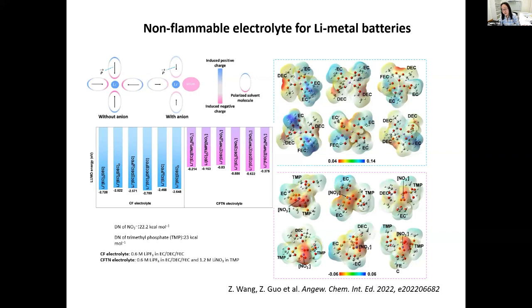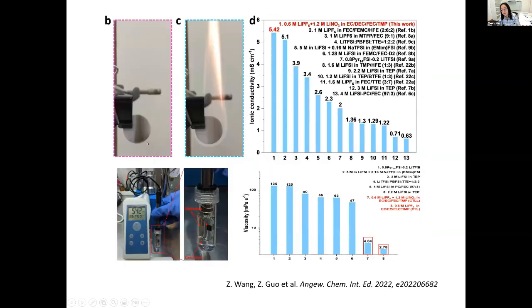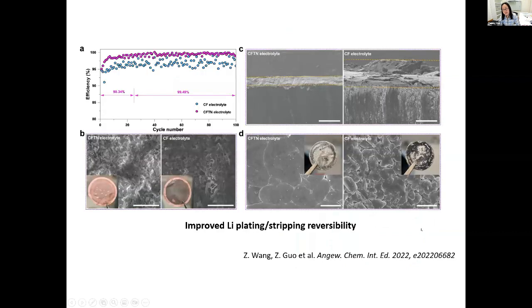Therefore, it can reduce the polarity of the electrolyte and make it more stable. And also from the calculation, we found that the LUMO value of the electrolyte increased, indicating the electrolyte is more stable. And from the MD calculation, we found that for all 6 possible solvation clusters, the ESP value decreased, suggesting that lithium metal is stable in this electrolyte. So then we found that this electrolyte cannot be ignited, it's non-flammable, and the viscosity of the electrolyte is quite low. The ionic conductivity of the electrolyte is actually high compared to most of the published liquid electrolytes, making it very promising for the lithium metal battery.